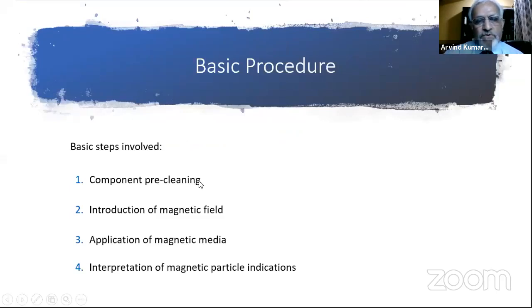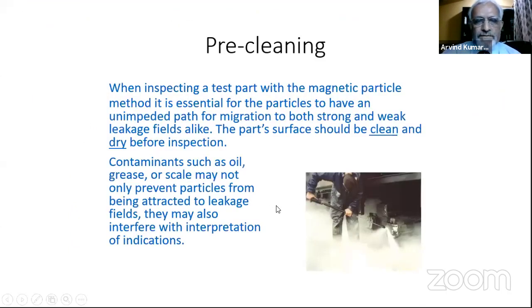So here also you have to clean the part first before doing MT. Then introduce the magnetic field. There are different techniques to introduce it. Then apply the magnetic medium. Again, there are ways: you have the dry method and the wet method, fluorescent. Then do the interpretation of the indication that has been formed. While cleaning, you have to ensure there are no contaminants. Mainly oil and grease are the main culprits you find in the area where we are supposed to carry out the testing, and you should ensure that the surface is clear of grease, oil and paint. Other things can be wire brushed and removed, but these things will not be removed that way.